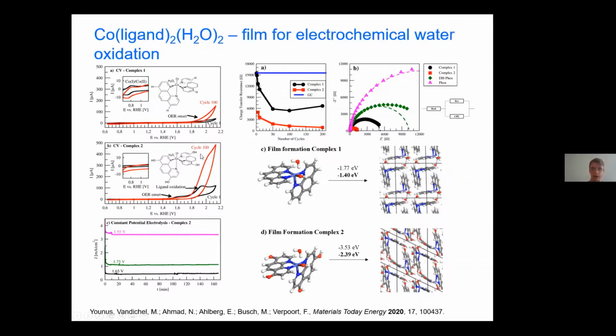And to explain why we have such an early onset potential for complex 2, but then at higher potential, we see that their behavior at more cycles is pretty similar, just there's more current flowing for complex 2. So to study that, I looked first at film formation, and I saw that film can form much better for complex 2. So that's more exothermic.